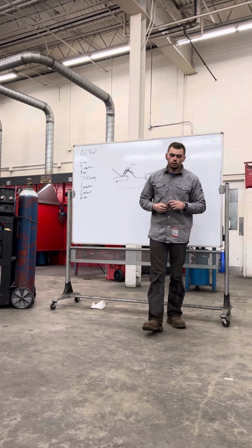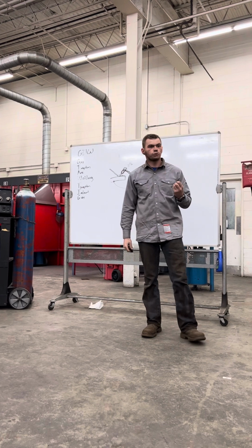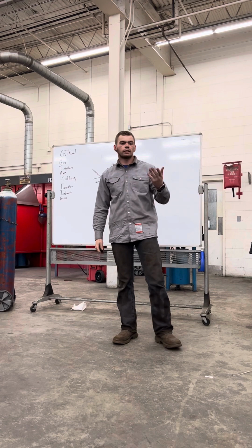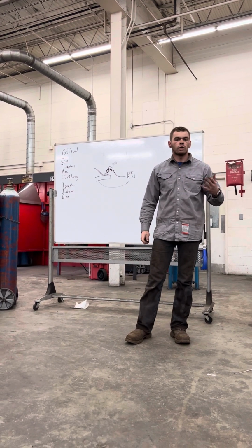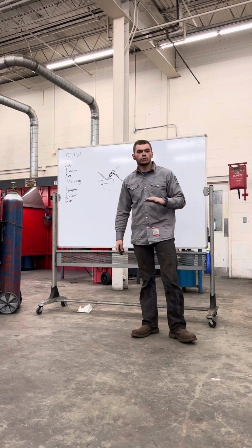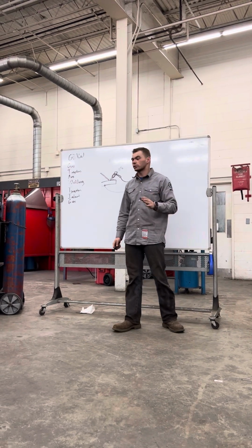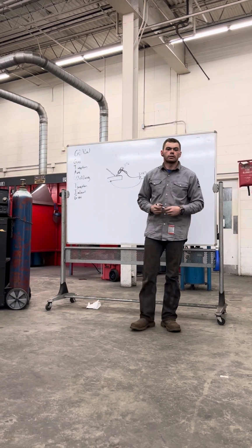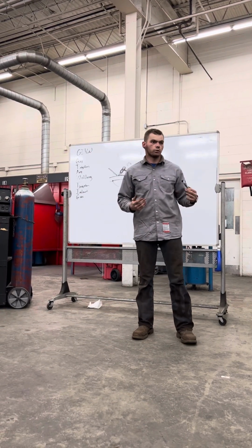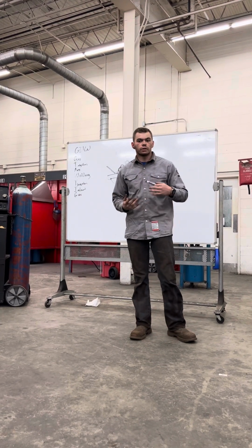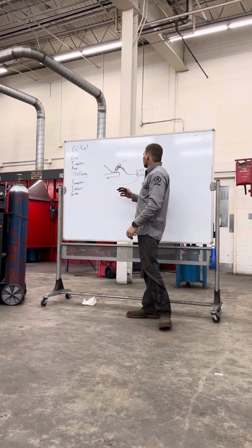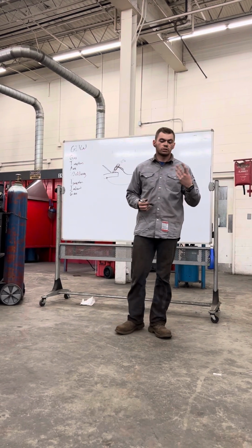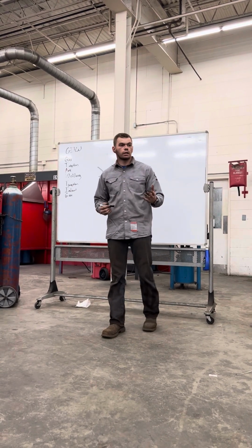This causes better fusion. It makes it less likely to have a problem of lack of fusion. There's no slag, so you have no slag inclusions or anything of that nature. So another thing is, when you're in flammable areas, like in some plants, you'll be around chemicals, flammable materials, things of that nature. So when you get around flammable materials, you don't want to have a lot of sparks like you would from stick welding, MIG welding, things of that nature.